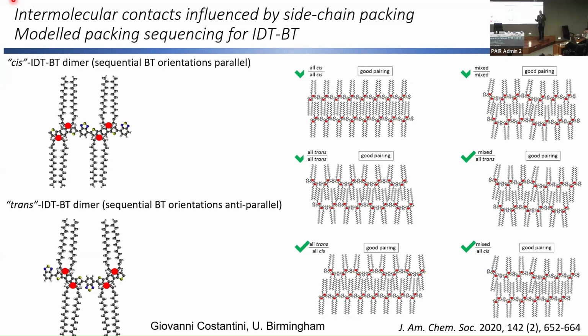But the very interesting thing about IDTBT is it really doesn't matter what degree of conformation you can think of. When you put two chains together above and below and you force the interdigitation, you can see that in each of these cases, there is a coherence of the side chains. So they can interdigitate nicely without any asymmetry or any lack of coherence at any point in the backbones. So we call this cis: down, up is called cis arrangement. Up, down, up is called trans. And when you force an all-cis into an all-cis, it looks very nice. And no matter what you do, even mixed up, you just mix up the conformations and put them together, mixed or all trans, it still works out such that you get very regular spacing between the side chains.